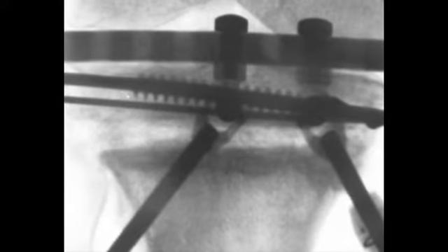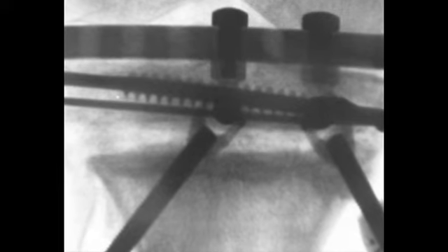The varus posterior translation deformity was corrected gradually. Fracture stability was achieved with circular external fixation using the Taylor spatial frame and associated computer software to achieve gradual postoperative correction to the mechanical axis of 4 degrees valgus. The nonunion site was progressively compressed 1 millimeter every 2 weeks for 8 weeks. Healing was clinically and radiographically evident at 12 weeks, and the fixator removed at 20 weeks. Full pain relief at the medial joint and nonunion site was achieved.